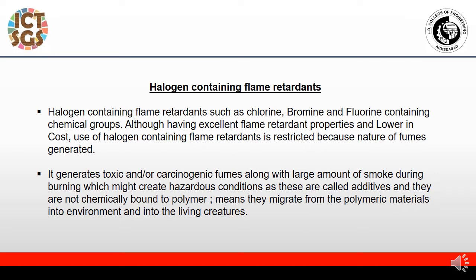Halogen containing flame retardants are those with chlorine, bromine, and fluorine containing chemical groups. Although they have excellent flame retardant properties and are lower in cost, the use of halogen containing flame retardants is restricted because of the nature of the fumes generated from them. They generate toxic and carcinogenic fumes along with a large amount of smoke during burning, which might create hazardous conditions. As these are additives, they are not chemically bound with the polymer, which means they migrate from polymeric materials into the environment and into living creatures.